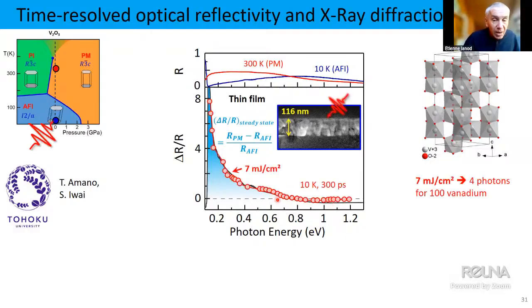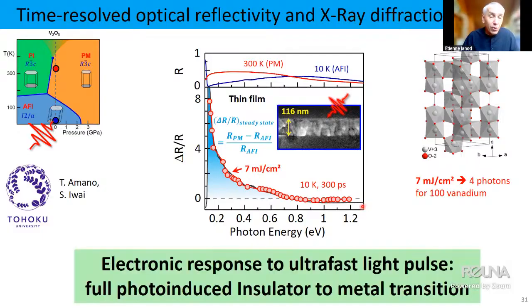And in fact, what is remarkable is that the new points that appear correspond to the points obtained after photoexcitation by a laser with a fluence of 7 millijoule per centimeter squared, which corresponds to roughly 4 photons per 100 vanadium. And you realize that the two curves are perfectly superimposed. It's a direct proof that by applying a laser pulse with a fluence which is not so large, it's possible to completely generate an insulator to metal transition.